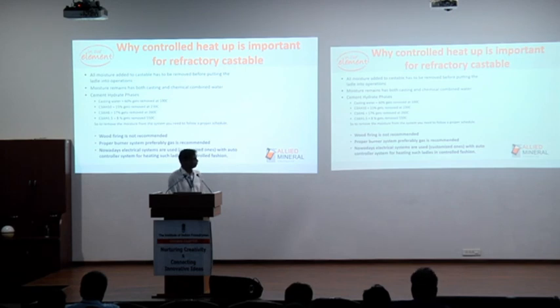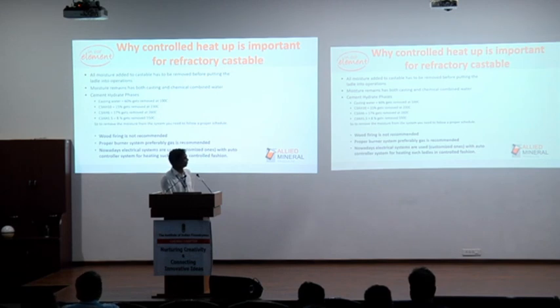This is again related to installation. All moisture in the castable lined ladle should be removed before introducing the liquid metal. People just think that within 100 degrees we can remove the water from the lining, because they think that's physical moisture. But there's always both chemical moisture and physical moisture combined with each other. So you can see the cement hydrated phases and the percentage of water removed at each temperature.